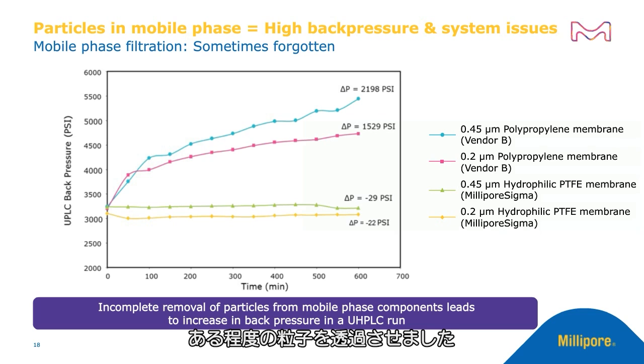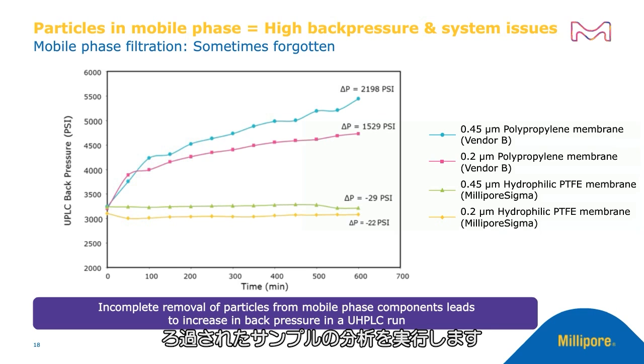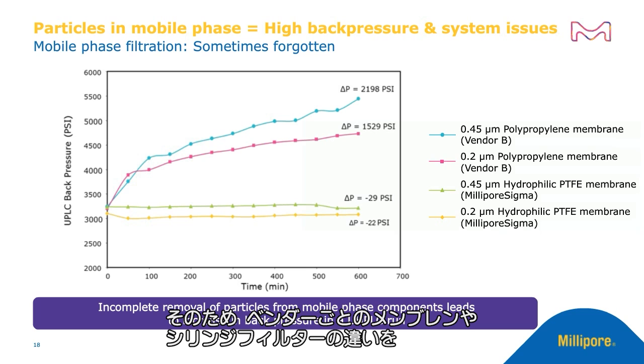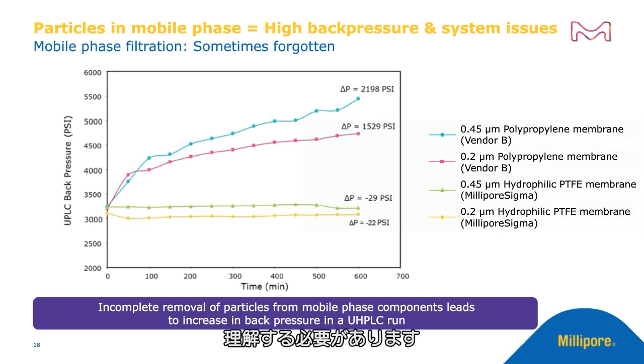On the other hand, the polypropylene membrane filter, which did allow some amount of particles to go through, these particles get collected at the head of the column, thereby leading to an increase in back pressure in this UPLC system by as much as 1500 to 2000 psi. So now imagine if this UPLC system was also running the samples that were filtered through the same polypropylene syringe filter, you can imagine how much increase in back pressure this can lead to. And sometimes, this UHPLC system can shut down completely altogether. So it is important to understand the differences between membranes and syringe filters between different vendors.